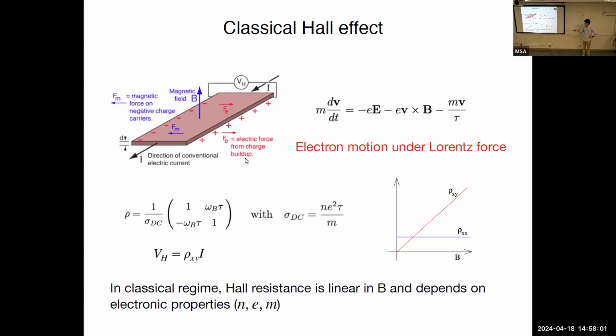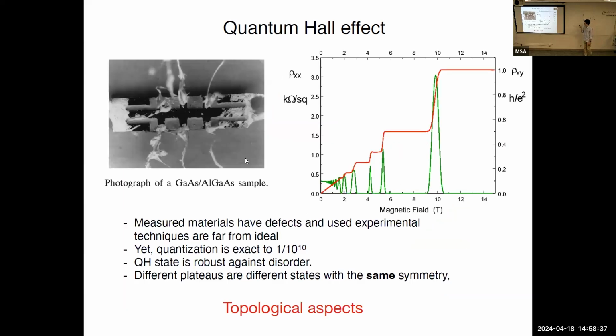And the notion of this classical limit is that the Hall resistivity is never anywhere quantized. It's actually growing with field, and also depends on the material parameters like carrier density, scattering rate, mass, etc. So it's really remarkable from an experimental point of view that you can make these 2D insulators very clean, and then gap them, and then observe the behavior which is really different from this one. Instead of something which is growing with magnetic field, you see just plateaus, as in here.